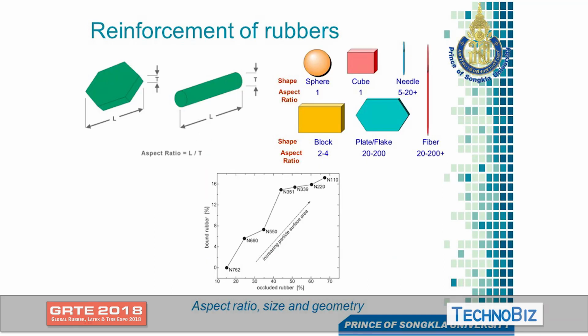And other than that, filler aspect ratio, and then filler shape or geometry, as I mentioned before, can also affect the properties of the rubber composite or polymer composites. Here we can see the fiber, needle-like fillers. As far as the surface area is increased, a large surface area can give more contact area. Once there is more surface area, that means contact area is improved, so the rubber or polymer matrix mechanical properties are enhanced by this kind of appearance.